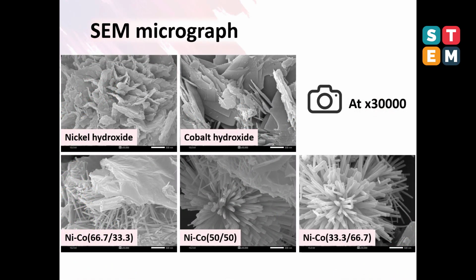For the results of this research, the SEM micrographs of all ratios were investigated at 30,000 times. Nickel hydroxide exhibits a nanoflake-like structure that assembles into a flower-like crystal, while cobalt hydroxide shows a random nanoflake-like structure also. All mixed nickel cobalt hydroxides exhibit the same nano-needle-like structure. The morphology becomes more uniform as a needle structure when the cobalt content increases.